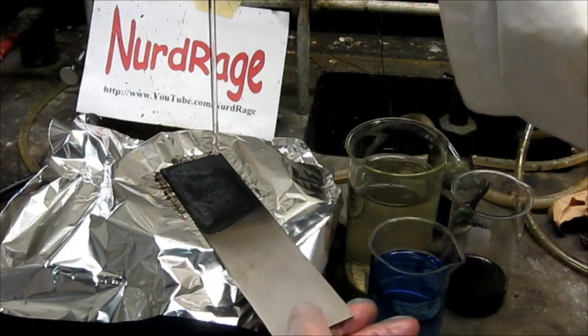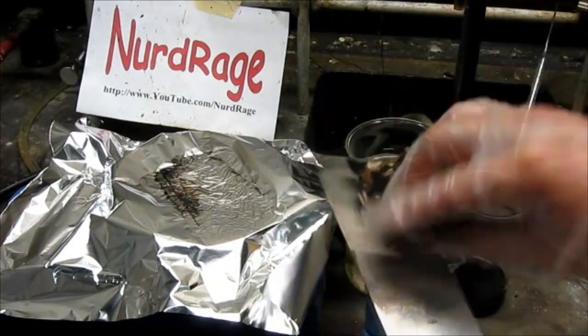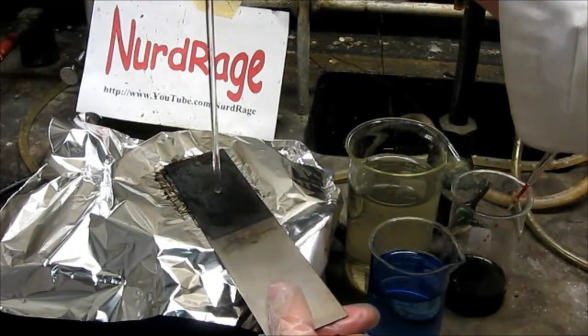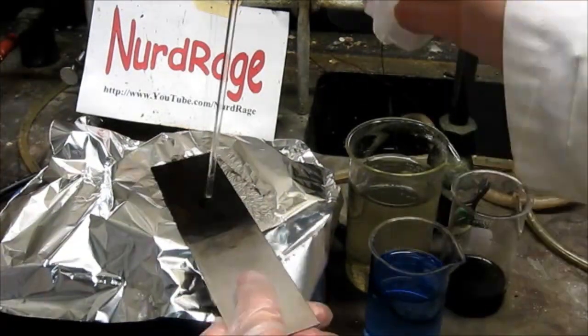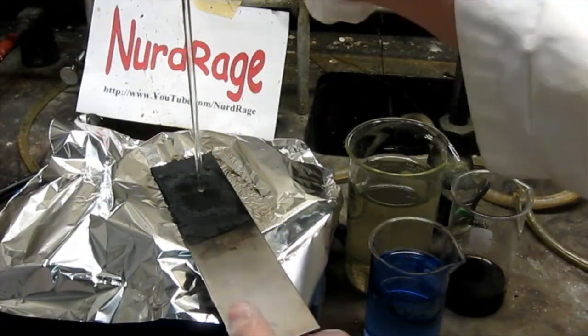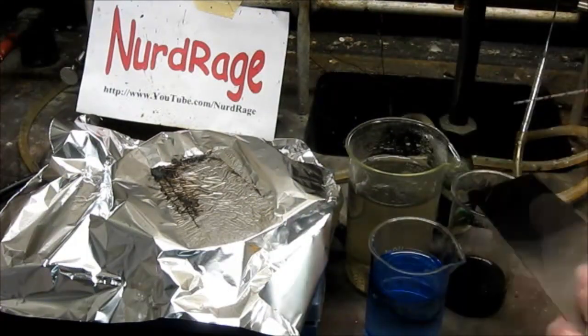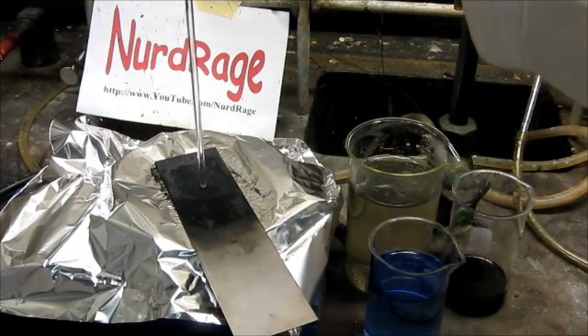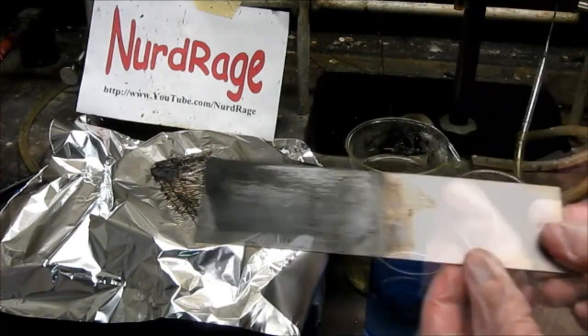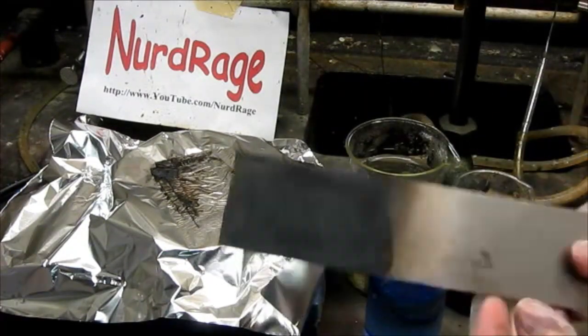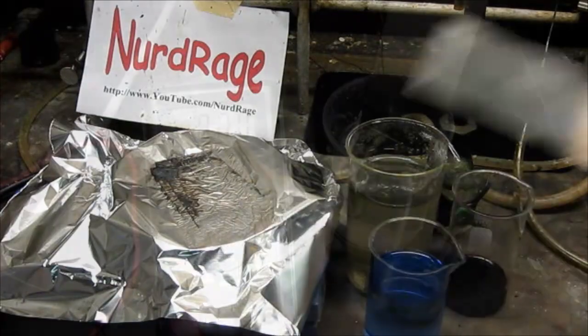As a side note, the steaming, wiping, and washing steps are optional. I've been told that other experimenters have avoided them without much ill effects. You might ask why we can't simply paint it on, and it's because baking it on gives better electrical contact and stronger adhesion than painting. Now we have a cobalt on titanium electrode.